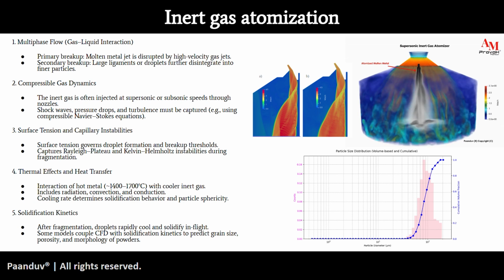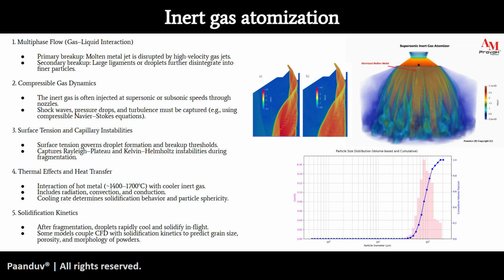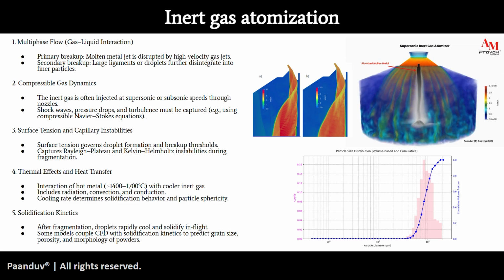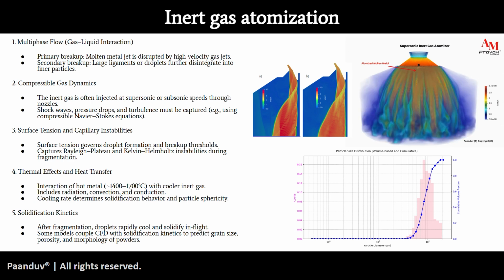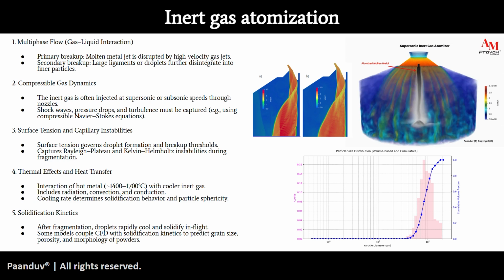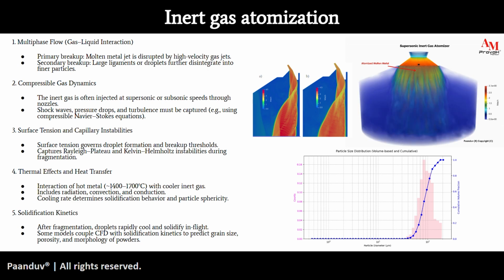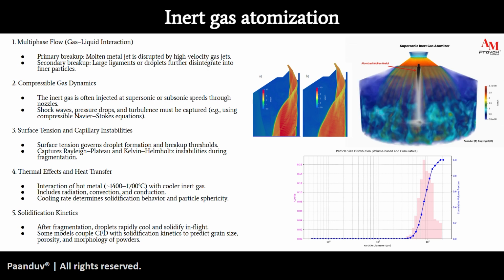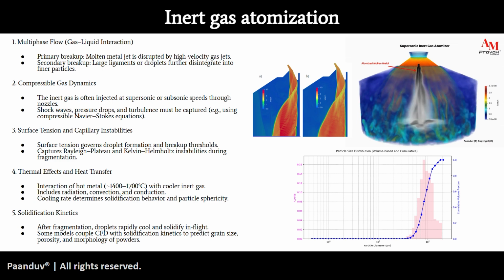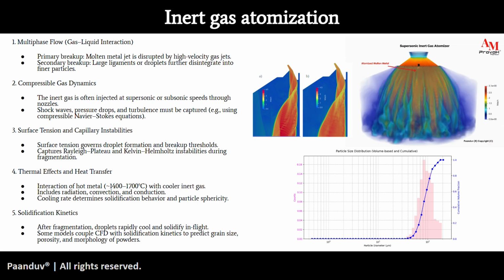You can imagine the physics and the coupling of the physics in particular is quite extreme here. You have gas liquid interaction, which is multi-phase flows. We are talking about primary breakup, where molten jet is disrupted by high velocity gas jets. We are talking about secondary breakup, where large ligaments or droplets disintegrate into smaller droplets. You have compressible gas dynamics. We are talking about high Mach number flows, so you have to use compressible form of momentum equations. You have surface tension and capillary instabilities. You have temperature dependent surface tension, because temperatures can go quite high in this. You have thermal effects, of course, heat transfer, interaction of hot metal with cool inert gas,